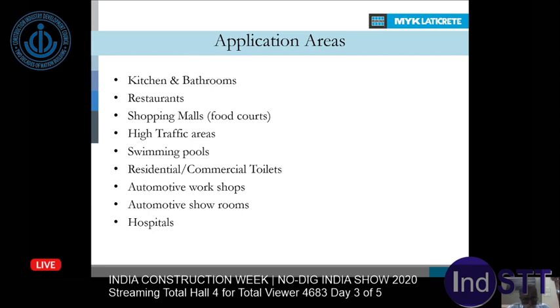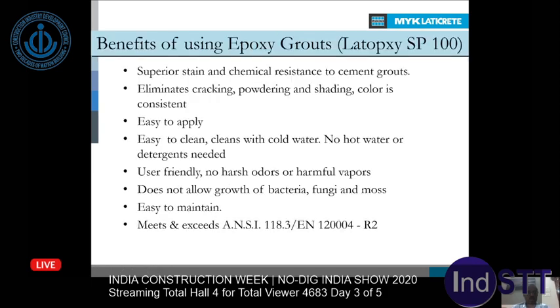And automotive workshops, there you can get a lot of oil stains and heavy areas, heavy workplaces. And hospitals, you need really clean areas. There is no dust, no other things, no moisture or fungus. So you really need a material that is highly durable and healthy. So these are the areas we recommend epoxy grouts and good adhesives. And what are the benefits of this material? Certainly it has superior stain and chemical resistance compared to cement grouts, and it eliminates all the cracks. There is no crack at all. Once it's done, it's highly durable, no powdering, no shading, and color is very, very consistent. And whatever aesthetics you want, it's maintained, and it's very, very easy to apply as you see in the picture.